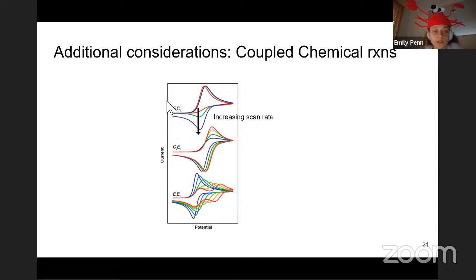For an example of this, first we have on top an example of a reversible electrochemical reaction, so that's EC, and then an irreversible chemical reaction. As we go from the red curve to the blue curve, that's with increasing scan rate. At slow scan rates, you're able to do your forward reaction, but then some irreversible chemical reaction results in you not being able to do the reverse reaction of the electrochemical reaction. If you scan really fast, then you might be able to do the reverse reaction of your electrochemical reaction faster than this irreversible chemical reaction can occur. So it's important to do CVs at different scan rates so you can try to tease out what mechanism is at play.